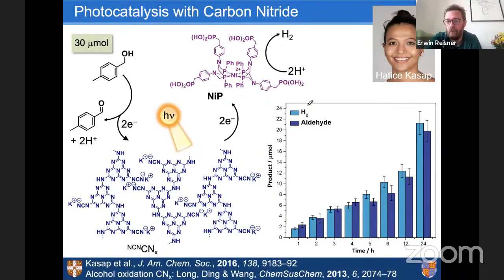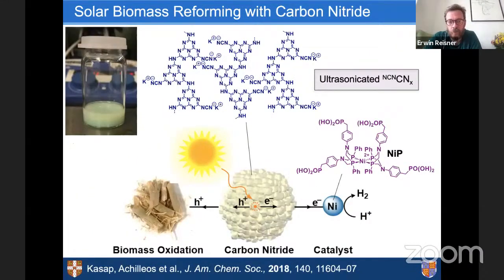And we could track the formation of hydrogen and aldehyde over time here. And we can see indeed, as you would expect for both being two-electron processes, quite a nice one-to-one stoichiometry of these products forming. So we did quite a lot on this carbon nitride, which I don't have time to talk about. So I want to get straight to the point with biomass. But since we saw that this oxidizes alcohols, we thought this should also be a nice photocatalyst for glucose or cellulose substrates. And this is indeed what we saw.